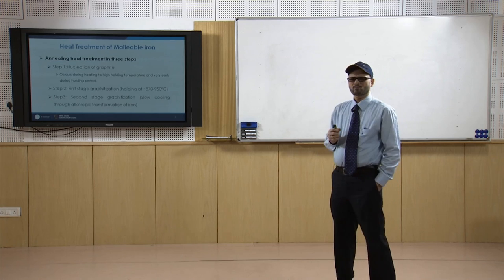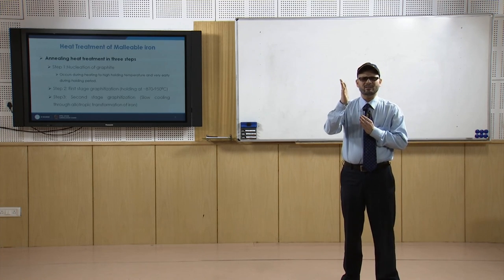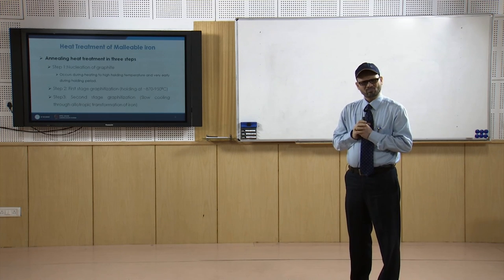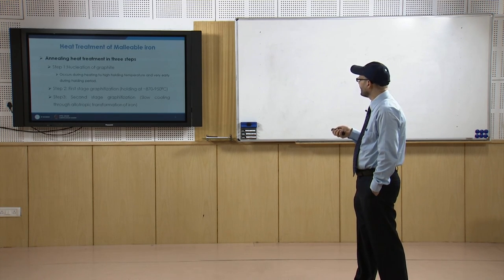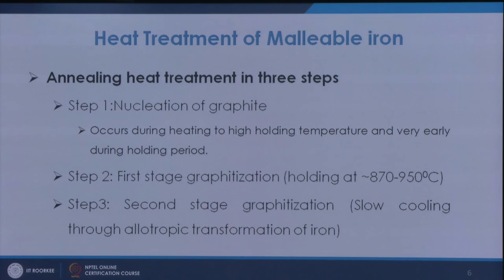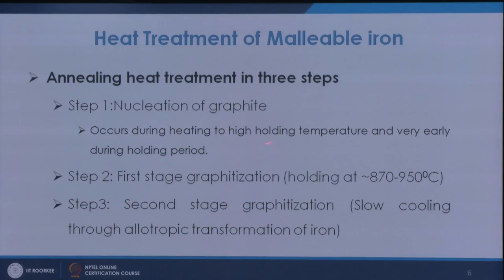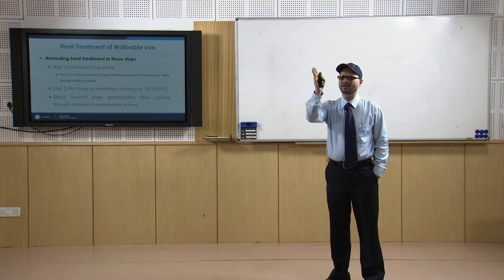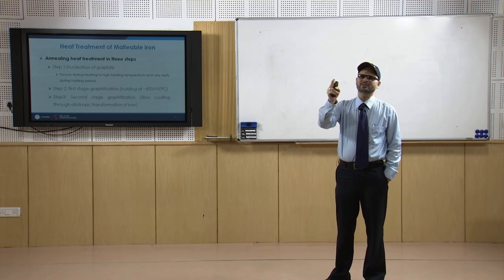This annealing heat treatment for white cast iron is done in 3 steps. We heat to a temperature of about 900 or 850 degrees centigrade, and then hold there for a very large amount of time. When we heat to the high holding temperature, during the early period there will be nucleation of graphite. So this annealing occurs in 3 stages. The first stage is nucleation of graphite, which nucleates during the early holding period.